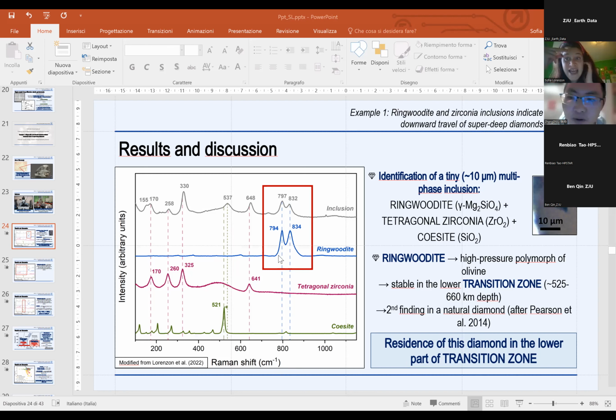This ringwoodite is probably more similar to a synthetic ringwoodite. In fact, if you observe the Raman spectrum of the ringwoodite found by Pearson in 2014, the Raman peaks of the natural sample were shifted to higher wavenumbers relative to our Raman shift values. And this is because the position of the Raman peaks depends on the vibration modes of the molecules that compose our material. But these vibrational modes depend on a lot of factors: the chemistry, the internal pressure, and a lot of other parameters.